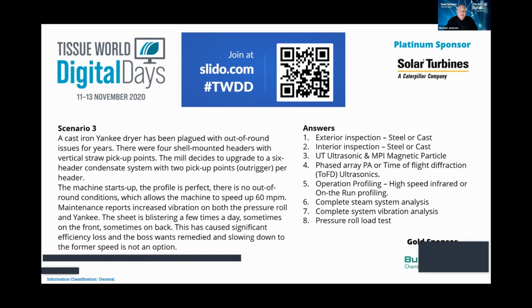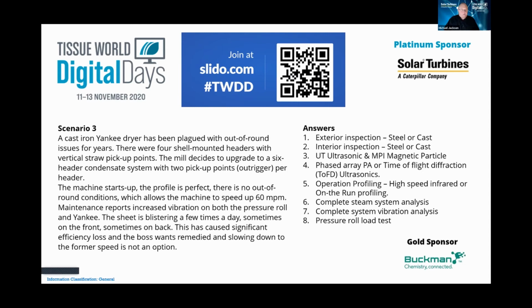Number 3, a cast iron Yankee dryer has been plagued with out of round issues for years. There were 4 shell mounted headers with vertical straw pickup points. The mill decides to upgrade to a 6-header condensate system with 2 pickup points as an outrigger per header. The machine starts up, the profile's perfect, there's no out of round conditions, and you're building up to 60 meters per minute. Maintenance reports increased vibration of both the pressure roll and the Yankee. So we see the sheet blistering a few times a day, sometimes on the front, sometimes on the back. And obviously that's caused significant efficiency loss.